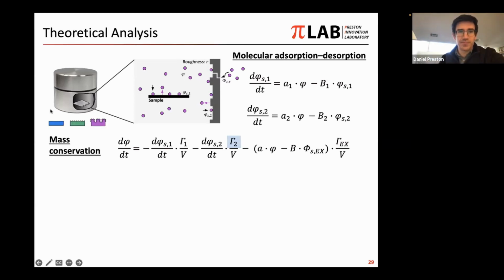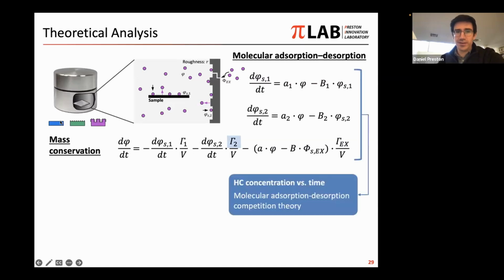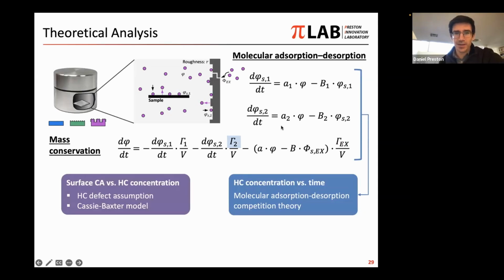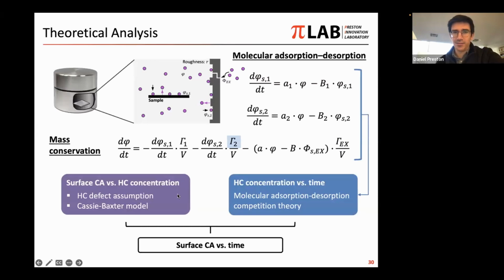And so we varied the roughness of the surfaces to change this surface area. And then in terms of the modeling, we could look at the hydrocarbon concentration versus time based on the differential equations shown here for the adsorption-desorption competition theory. We could also look at the contact angle versus the hydrocarbon concentration. And this could be maybe assuming a Cassie-Baxter-like model with these defects on the surface, which would look something like this. And then we can combine these together and essentially through our modeling or theoretical analysis, understand the surface contact angle as a function of time for samples that are stored inside of this container.